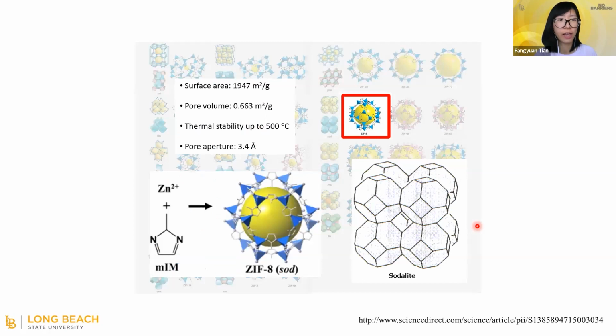And in this study, at the very beginning, we started with a type of ZIF called ZIF-8. It is composed of zinc ions connected by 2-methylimidazole, forming this sod-like structure. It has an extremely high surface area, almost around 2,000 meters square per gram, and a large pore volume. More importantly, it has relatively stable thermal stability. When you look at the pore size of this type of material, it's around 3.4 angstrom. So it is close to carbon dioxide. So we're thinking that maybe you can use this type of material to trap carbon dioxide and free up methane.